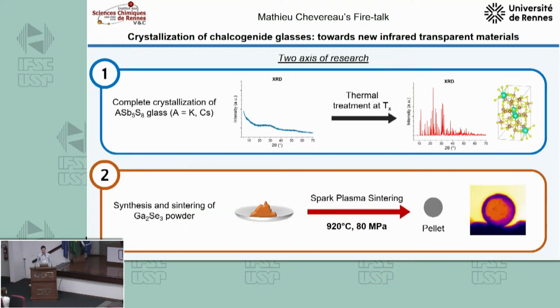I also have a second axis, which is the synthesis and sintering of gallium selenide powder. This is also a crystalline powder, which I sinter by spark plasma sintering, and we obtain pellets that are also transparent in the medium infrared region. If you want to know more about this, feel free to come see my poster. Thank you for your attention.